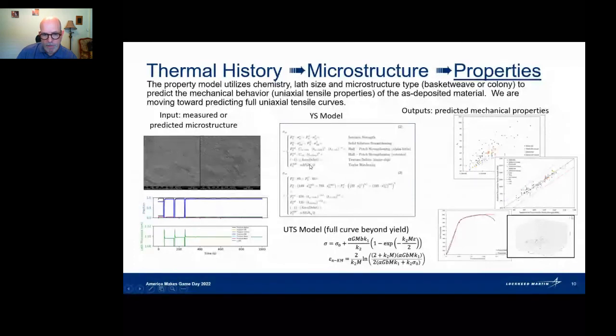Actually, the composition is one of the primary things that determines that strength, as you might imagine. But then secondarily, the microstructure, what the different phases are, as well as the grain morphology within the material state, all come into play in defining the yield stress and the ultimate tensile strength. Another significant thing that Pete was able to show was that the texture can change the strength values by as much as 10 to 15%, and then strain hardening as well is a major influence on what the resulting yield strengths and ultimate tensile strengths are.